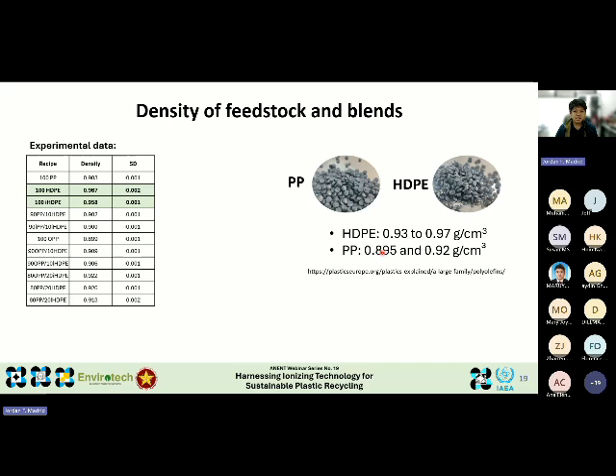One of the clear indicators is the change in density after electron beam irradiation. Remember, HDPE has a mostly linear structure of polymers. When chain branching occurs, whether short chain or long chain branches, it creates a more irregular molecular structure. This irregularity makes it harder for the polymer chains to align and pack efficiently, which in turn lowers the density—and this is exactly what we observed.